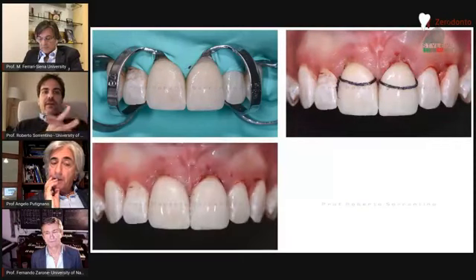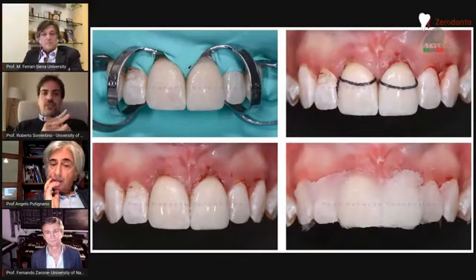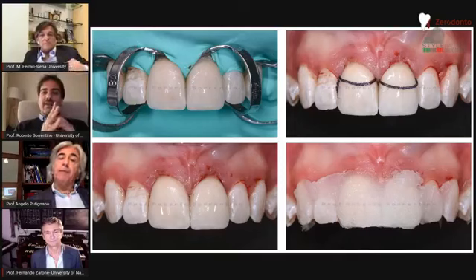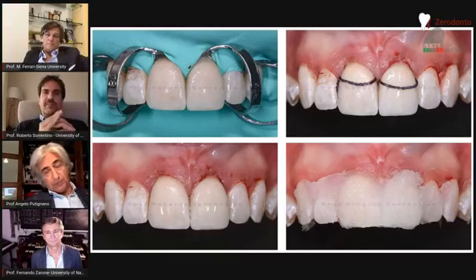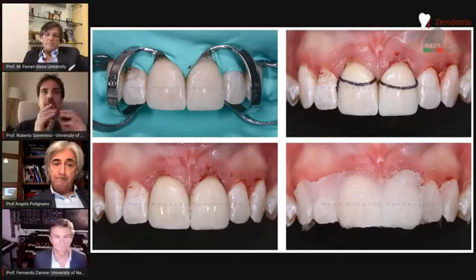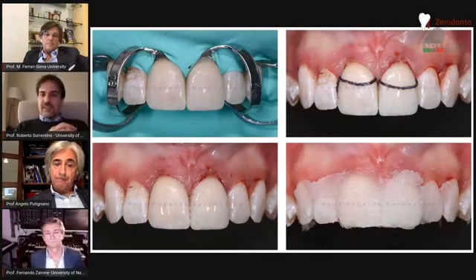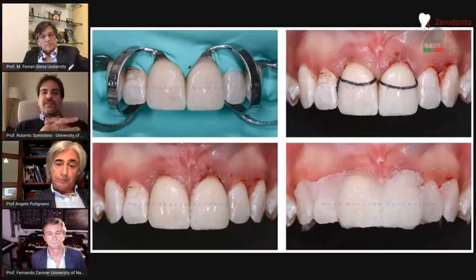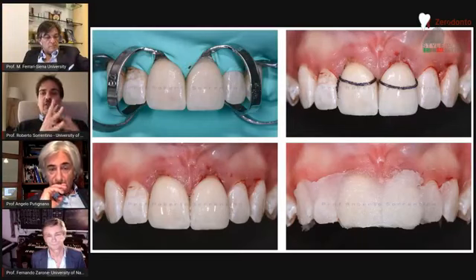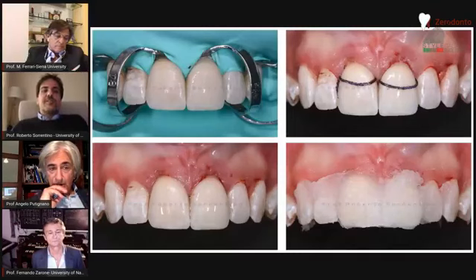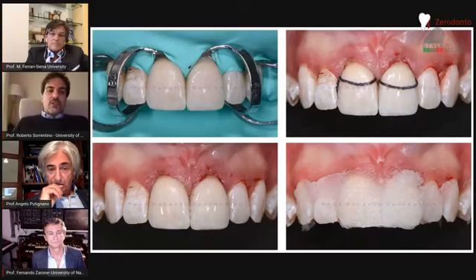I always use very thin 3-0 retraction cords, silk cords, to prevent the entanglement of resin remnants under the gingivas. Very troublesome if you are dealing with self-adhesive cements. And finally, I perform post-curing with an oxygen barrier just after freeing the gingival margins completely. Cementation is always a little bloody for soft tissues, but this is just an acute injury.